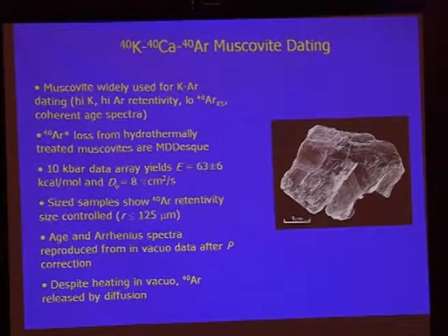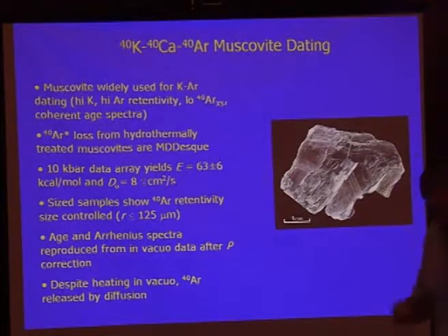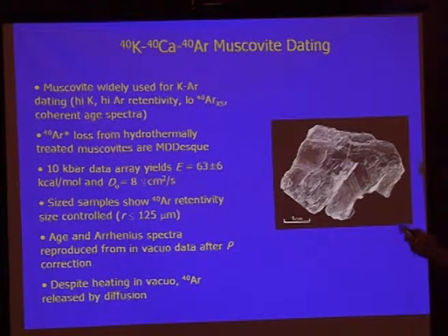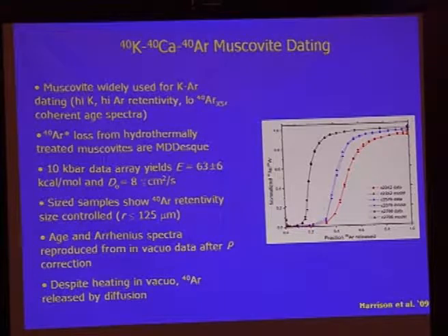So for years, we were living with a closure temperature of 350 plus or minus 50 degrees. And it sort of worked because we knew it was more retentive than biotite, which had its own nominal closure temperature, but it didn't really. Anyway, we made some progress recently, and that is we devised a way to take the experiment, instead of doing 2-3 kilobars, take the material up to 10 kilobars, 20 kilobars, and we actually can then stabilize the muscovite to higher temperature and get some argon moving.